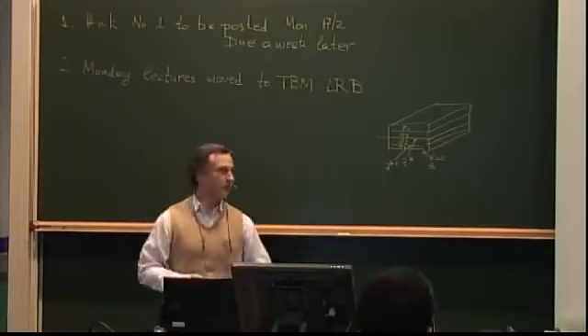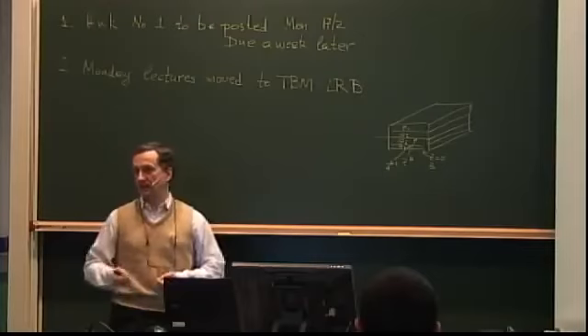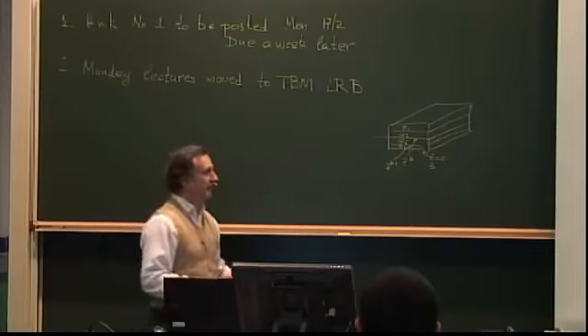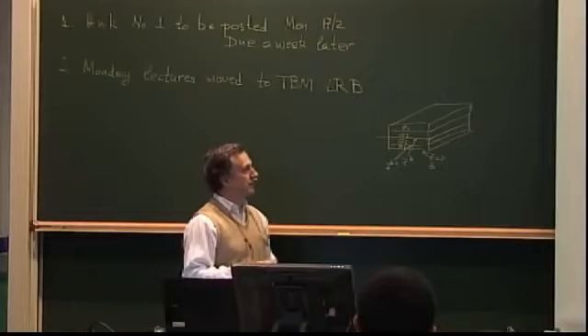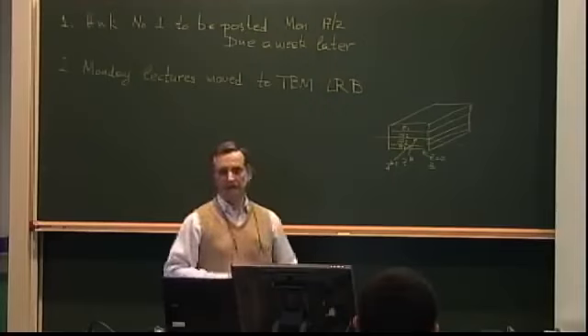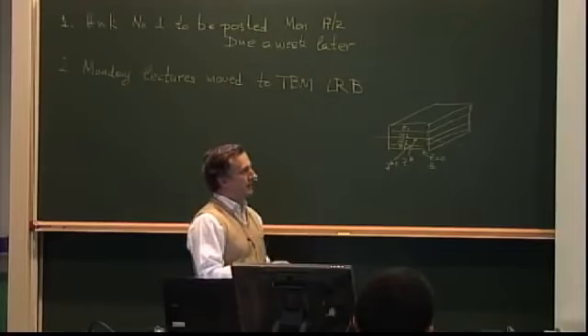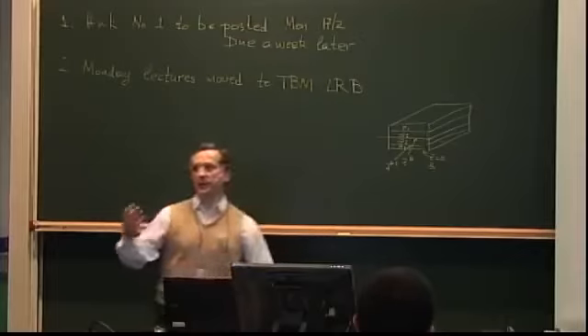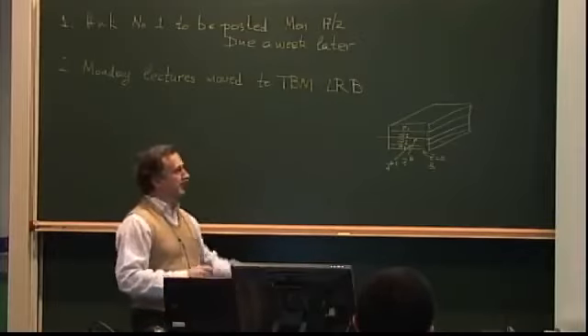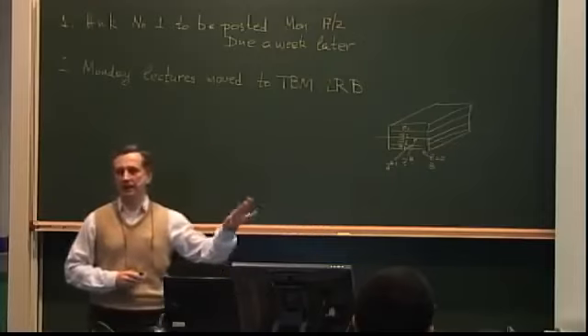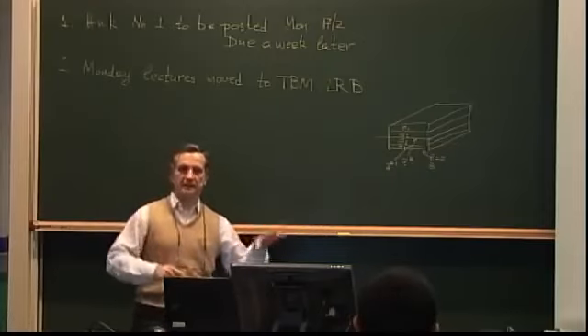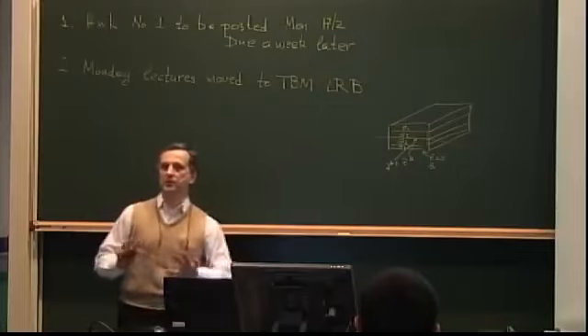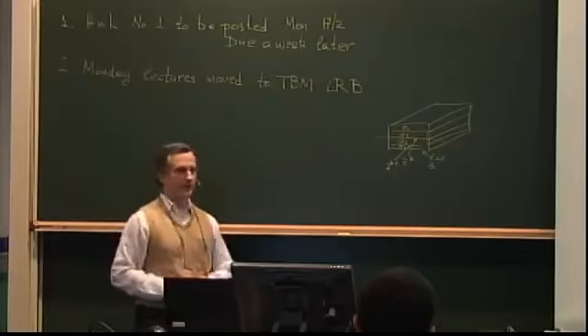And to start with that, we have to think, what do we typically get in the laboratory as actual measurements? And the first thing that you know is that if I load something in tension and somehow I measure the stress, F divided by WH, my average stress, and the mid-plane strain, I would get, if all is well and the material is well behaved, a straight line, the slope of which is the Young's modulus, and that's fine. We are making some assumptions here. We are saying the laminate is not unsymmetric. The laminate is symmetric, so the coupling situation is pushed aside for now just to make a point.